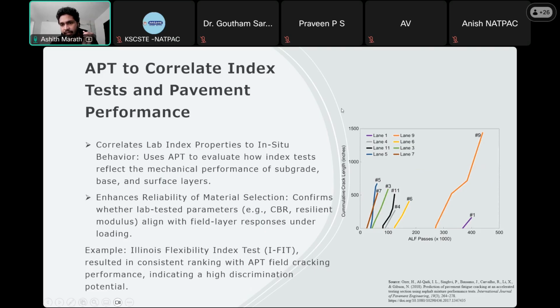I have given a graph here on the right side, which is again from our test facility in Turner-Fairbank. This was a result of one of our previous studies, which shows the cumulative crack length with respect to the ALF passes. Here ALF means accelerated loading facility, which is the same as the APT. Earlier we used to call it ALF. So it's similar to the APT. What the study did was they tried to correlate the Illinois Flexibility Index Test results with the cracking results you usually see in the figure. And the result was that the IFIT was consistent in ranking the APT field cracking performance and indicating a high discrimination potential.